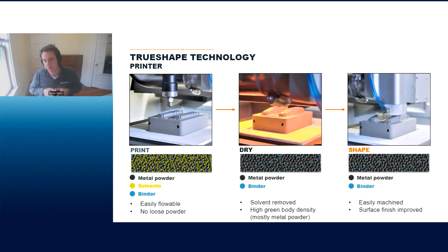So every single layer, we're printing a layer, drying a layer, and machining a layer, which is why if you look at our parts, which I wish everyone had one here in their hands, you can see the features are super, super crisp. You're getting those EDM sharp features. You don't see layer lines or anything like that. You're getting this excellent surface finish. And that's because every single layer is being printed, dried, and machined.